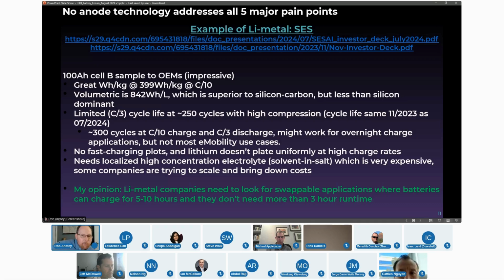So really the conclusion I come to is, first off, some major issues need to be overcome. Someone needs to scale lithium metal to large volume and lower prices. Someone needs to scale solvent-in-salt or next generation solid state, because that's necessary to get any cycle life. If you try to use commercial electrolyte with lithium metal, you'll get 20 cycles. And then last but not least, I don't know that fast charge can ever be overcome, because when you charge lithium fast, it forms dendrites. Dendrites short cells. Short cells, well, you know what happens to that.